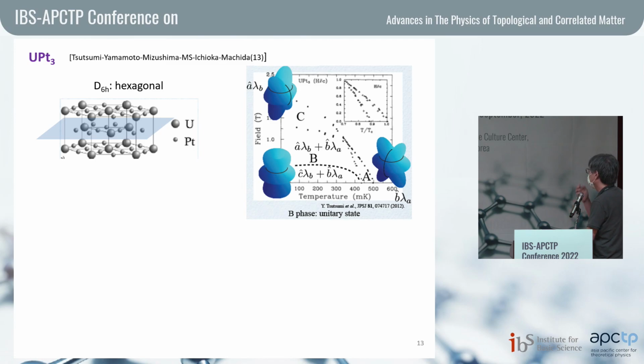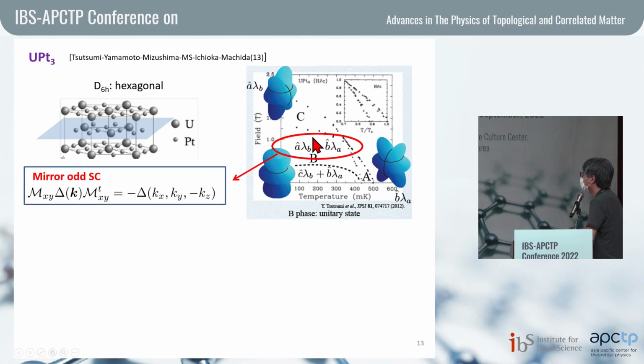Now I consider this particular phase B. According to the theory, phase B realizes a mirror odd superconductor, so we have an additional minus sign here. According to the argument in the previous slide, we can expect spin-full Majorana fermions. And actually, we can confirm this expectation by creating a vortex in the z direction. This configuration also does not break the mirror reflection symmetries.